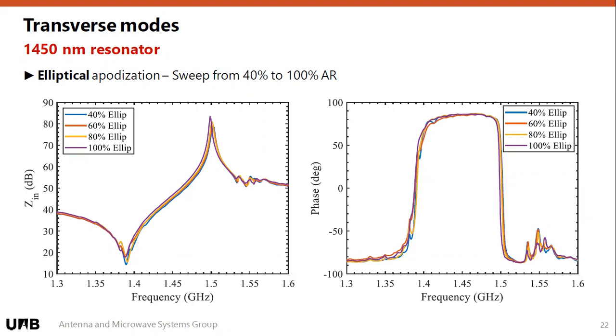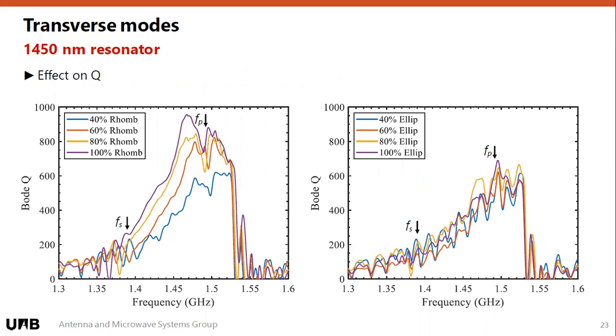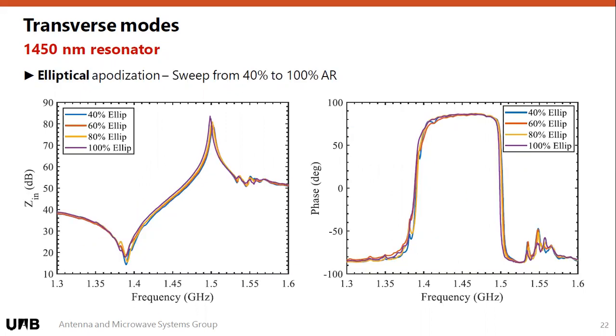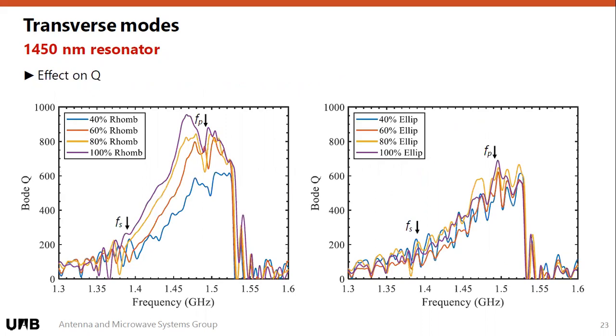So the elliptical apodization was a nice study and a nice way of playing with the resonator, but we decided to go for the full rhomboidal apodization. We saw that the more you go up in apodization, you could actually start losing coupling. So we didn't want that. But in terms of Q, just by the fact that you are confining your mode better and you don't have energy going inside your spurious modes, see how the Q grows just by increasing the apodization ratio.